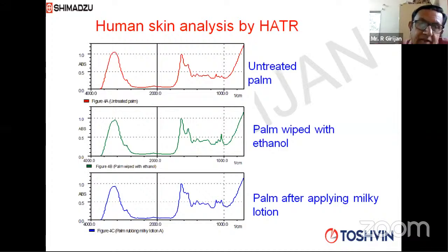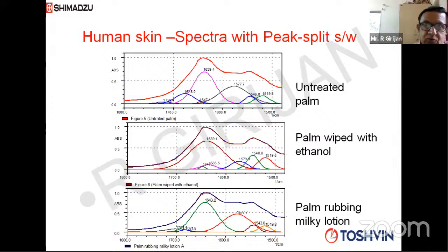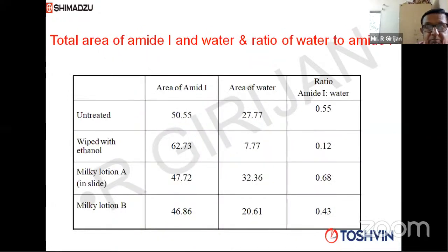If you look at all the three spectra, you feel they're all the same, but there are minute differences, and you need special software to study this. You require peak split software for this. When you apply peak split software, the spectra can be deconvoluted, and then you get information. There is an amide peak, and there is a ratio. What we are trying to find out is the ratio of amide to water. Amide is coming from your human skin and water is coming from your lotion.